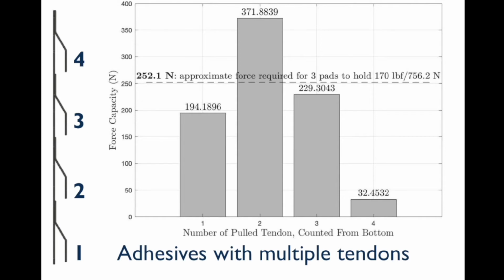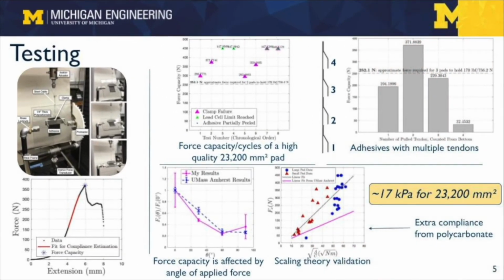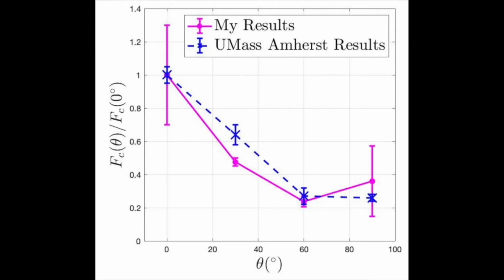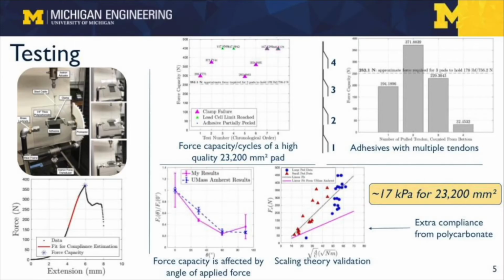Only the tendon closest to the center had a critical load above the 252.1 newton requirement. With the highest and lowest tendons being the weakest points, I elected to eliminate those in my climbing paddle design, instead only relying on 2 tendons closest to the center. However, the uppermost tendon is still a weak point, but we'll get back to that later. My results from my examination of the effect of loading angle with respect to the surface seemed to agree with the results obtained by UMass Amherst. My experiment showed a significant decrease in force capacity as the loading angle increased.